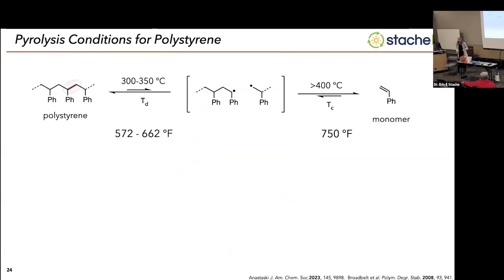Now, like I said, polystyrene is recycled, and the common way to recycle it is through pyrolysis. It's very small, not much of it exists because it's so energy inefficient, but it can happen. And so in pyrolysis, we want to start breaking down that polymer. We need to heat it to greater than 750 degrees Fahrenheit. So imagine you're making your turkey for Thanksgiving. If you put it at 750, that thing's going to be toasted really quickly, right? That's a lot of energy. It takes a lot of energy to heat up that plastic and convert it back into the monomers. And this is the problem with plastics recycling.